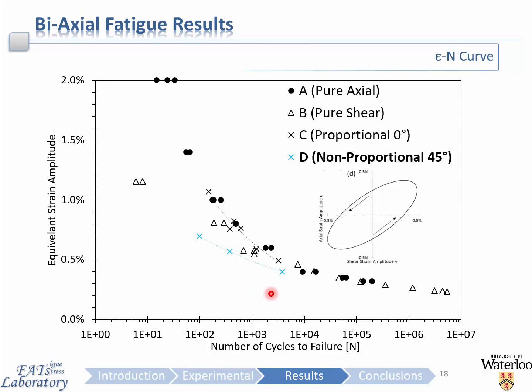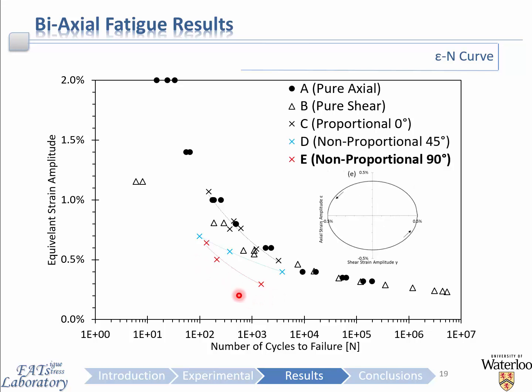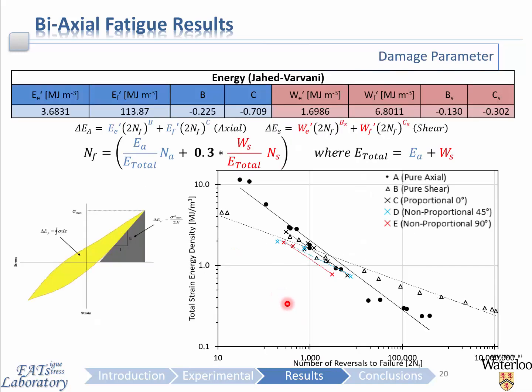The damage is now accumulating along different planes, resulting from the rotation of the principal axis, and this results in a detrimental effect on fatigue. This effect is now even more exaggerated in the 90-degree out-of-phase case, where the increase in non-proportionality further decreases the fatigue performance. Now, there are a large number of damage parameters available for modeling fatigue.